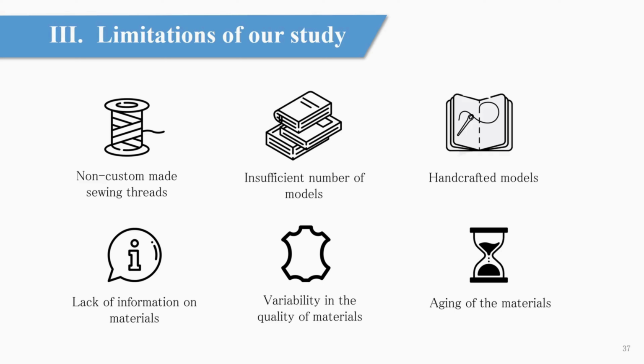The third limitation is that the production of the samples requires numerous handcraft steps. Some variations are possible between the models on aspects that are difficult to quantify, such as the tension exerted on the thread during sewing. The lack of information and the variability in the quality of materials used in conservation is also a point to consider. For example, it's impossible to obtain two identical skins. The mechanical behavior therefore depends both on the skin obtained and on the sampling area. Similarly, it is rare to know the twist rate of a thread or a cord. The use of custom-made cord samples could provide greater repeatability of the results and improve their relevance. Finally, the study does not consider the aging of the materials.